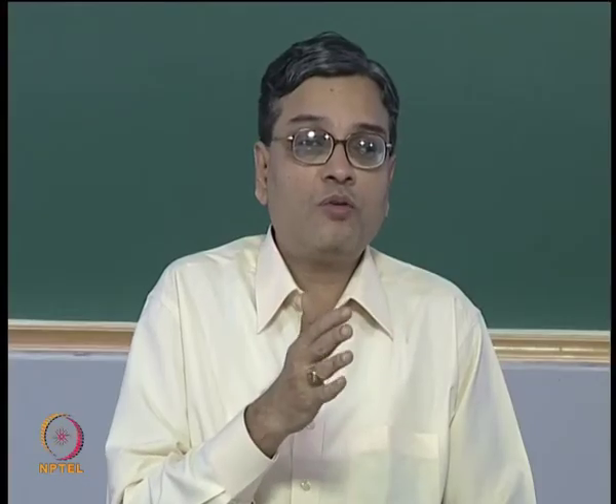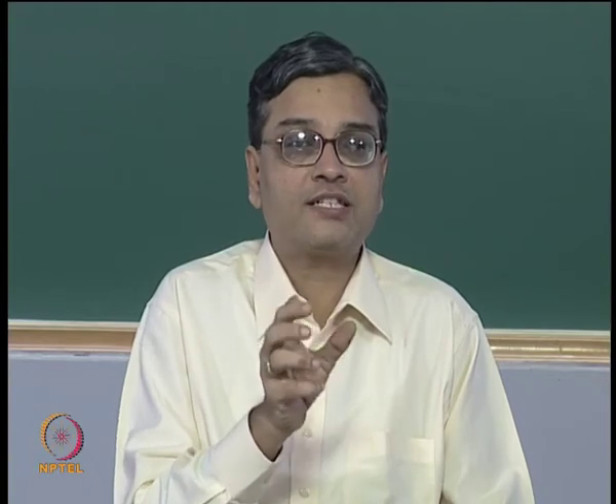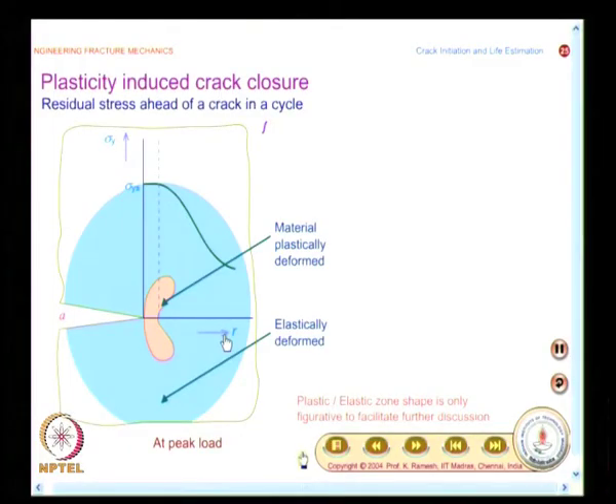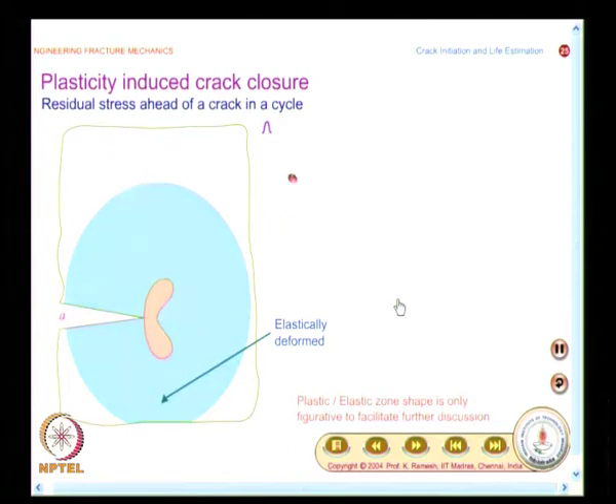When you remove the load, what will happen? The portion of the material subjected to elastic condition would come back to its original position. The portion which is subjected to plastic loading condition will also recover by a very small amount equivalent to its elastic strain component. Because of plastic deformation, it will have plastic strain component. And what would eventually happen is, in the process, the elastic material, when it recovers, it will apply excessive force in this zone. This will turn to compressive plastic zone, which you can visualize from the way the animation is made.